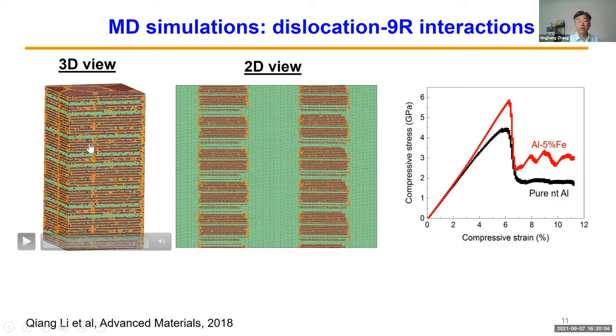in red atomic layers with the green as FCC matrix, but this is pure aluminum. If you introduce stacking faults in aluminum, you can probably freeze them at very low temperature, 0 K, but when you heat it up to 300 K, they disappear. They wipe out right away. They're unstable. But that's not the case for aluminum iron. If you introduce 5% of iron or so, this structure is stable.